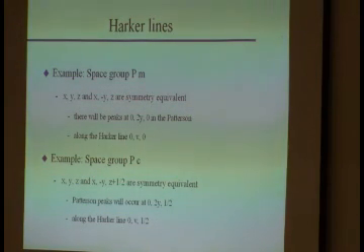For example, if we have space group PM, nice monoclinic space group, we have 2 equivalent positions, okay, from this mirror plane. So what we get is that every atom at XYZ has an equivalent atom at X Y bar Z. And we've used that before, right, for systematic absences. Well, we haven't done that with a mirror because a mirror wouldn't give you systematic absences. But here are 2 equivalent positions.